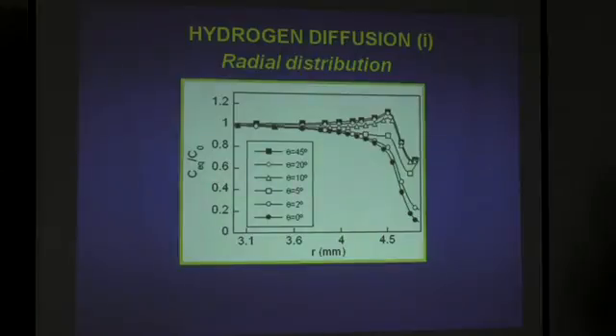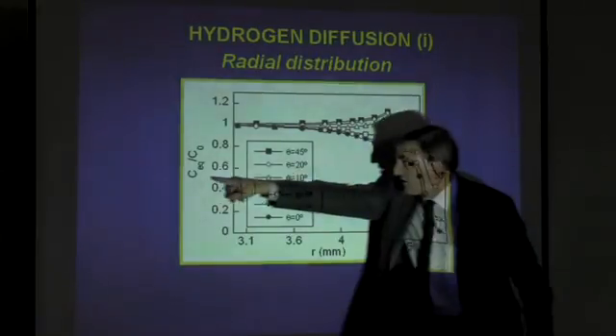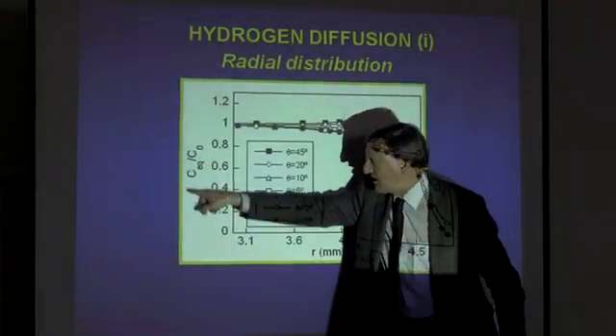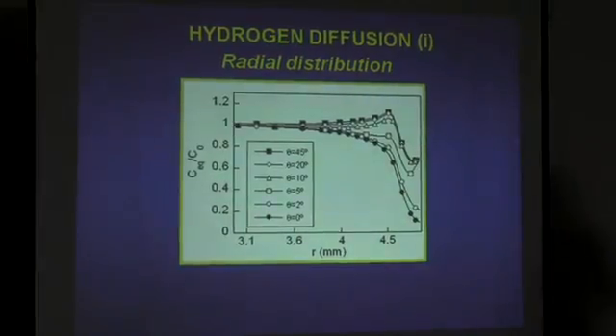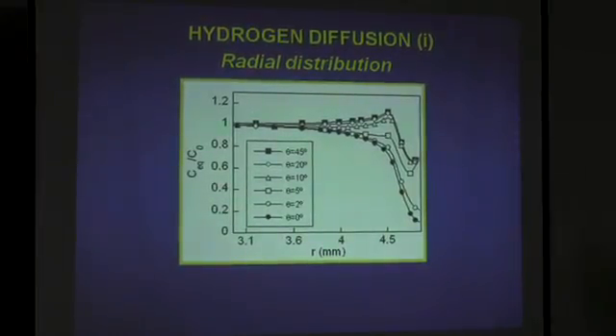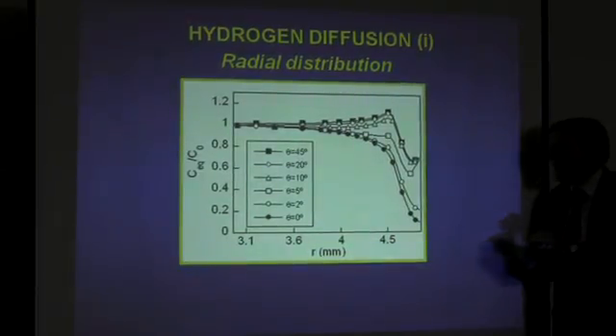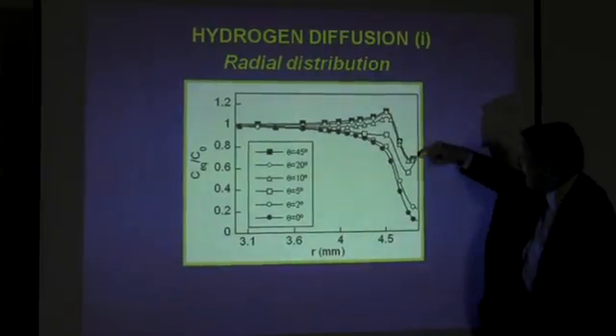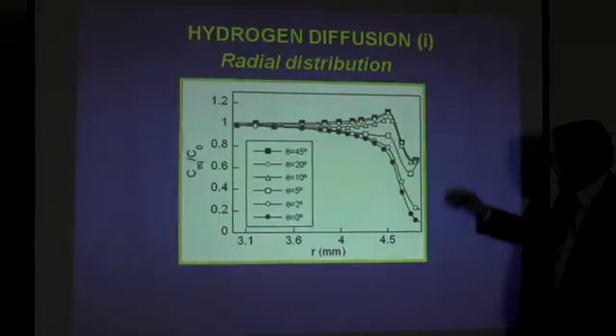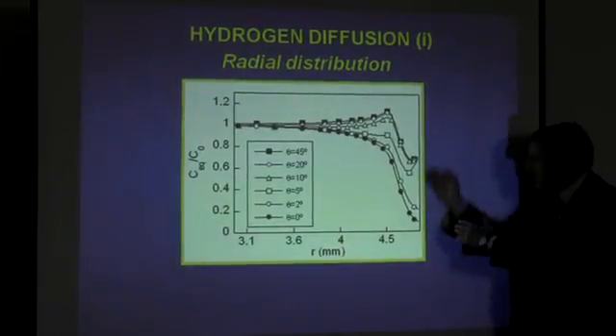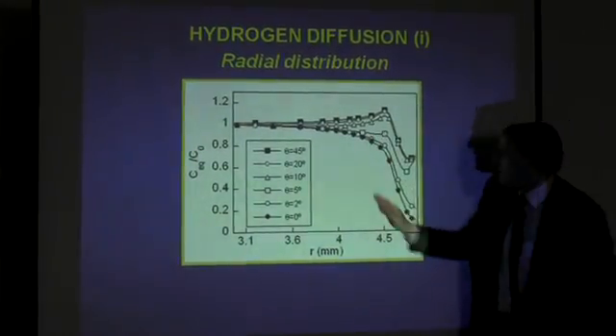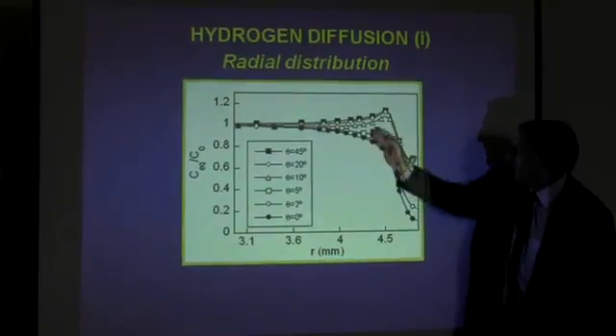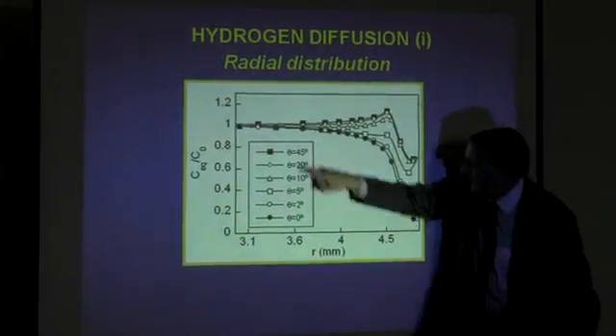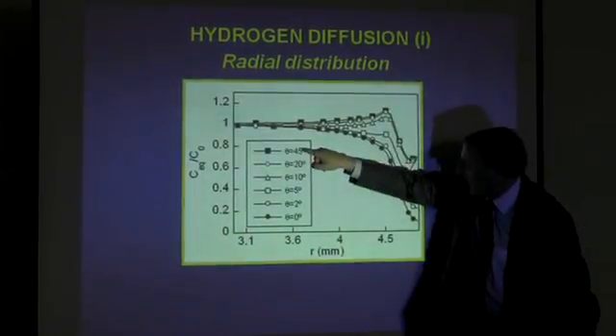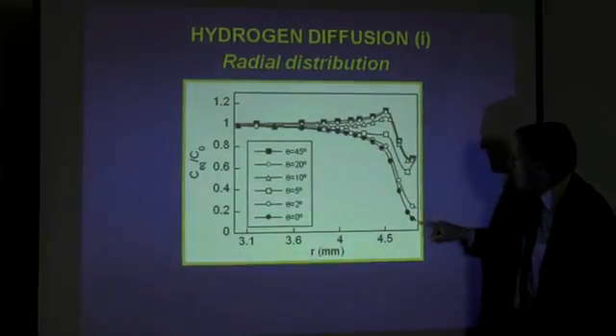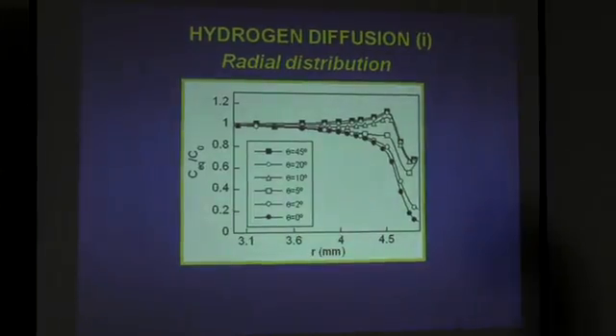With regard to hydrogen diffusion, we have this radial distribution of hydrogen concentration for infinite time, the equilibrium hydrogen concentration, normalized in dimensionless terms, divided by the equilibrium concentration for the stress-free metal. Again, it tries to follow the hydrostatic stress profile. We have a minimum at the boundary, a small amount of hydrogen at the boundary, but strongly pumped, strongly driven because of the inward, positive gradient of hydrostatic stress. For different angles, the maximum is for 45 degrees, and for 0 degrees we have the lowest distribution, and for intermediate angles, intermediate distributions.